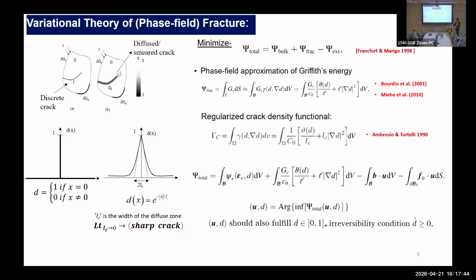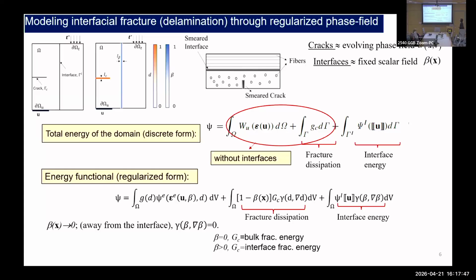Okay, so this was the core of this phase field fracture theory. Now we tried to extend the classical phase field theory to model fracture in FRPC composites. That was our sole motivation. So along with the sharp crack approximation, remember, as I said before, that most of these fiber reinforced composite materials are used in laminate forms, and these laminates often have off-angle lamina orientation. So they have fiber orientation mismatch, and that mismatch actually gives rise to this interface.